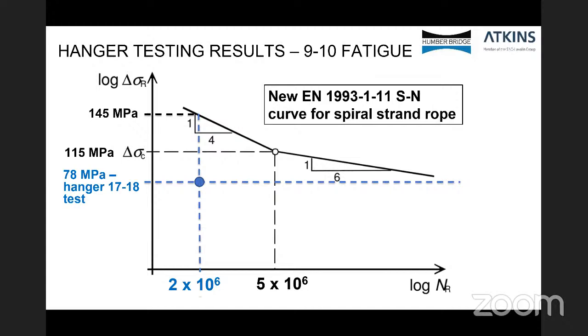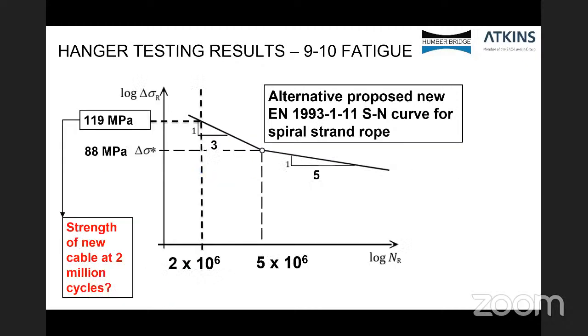This shows the new curve proposed to be carried out to 145, but then critically at 115 megapascals, they proposed to have 5 million stress cycles. And if you look to the next slide, for the second cable, we proposed to carry out our testing to 119, which was an alternative proposal for the 1993 SN curve.